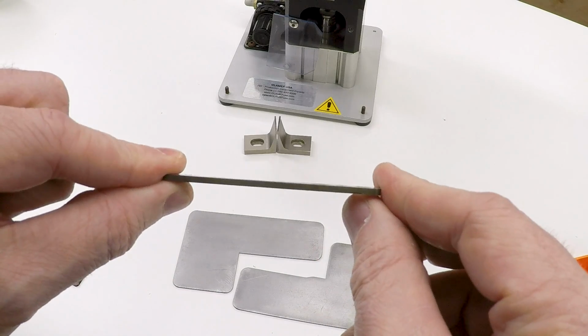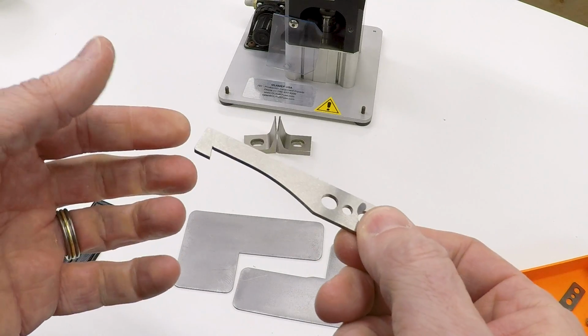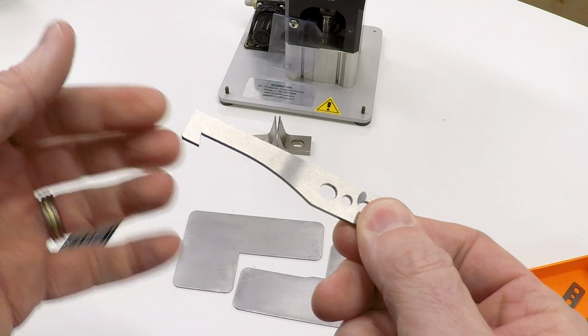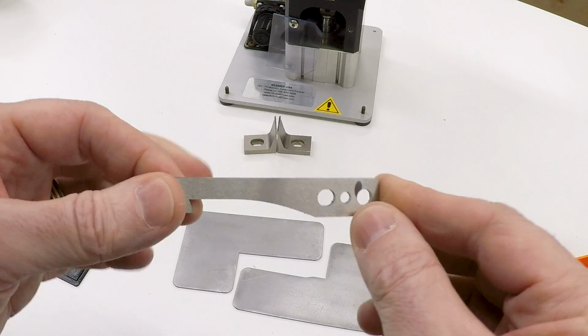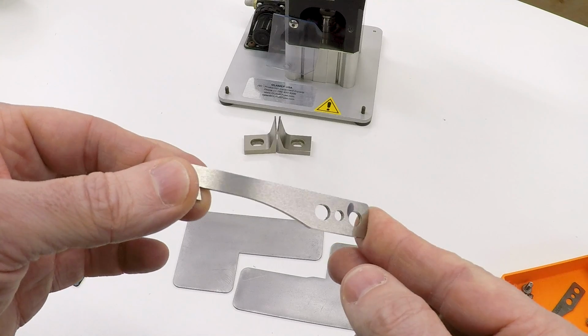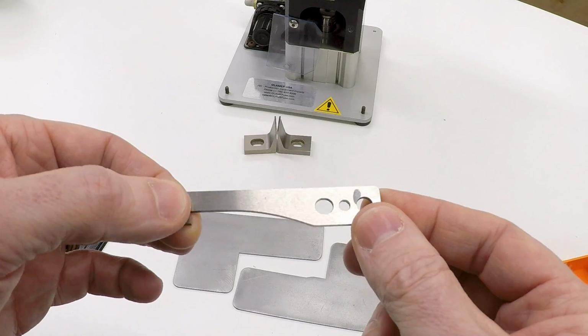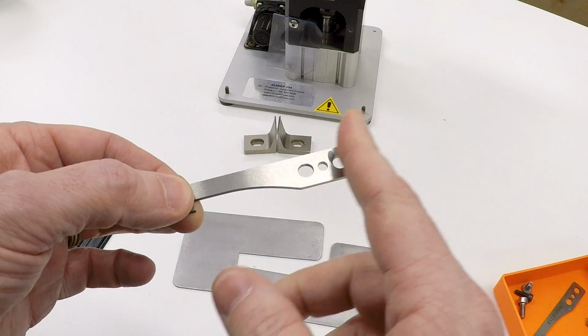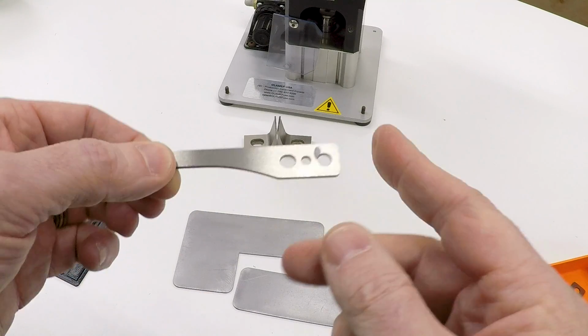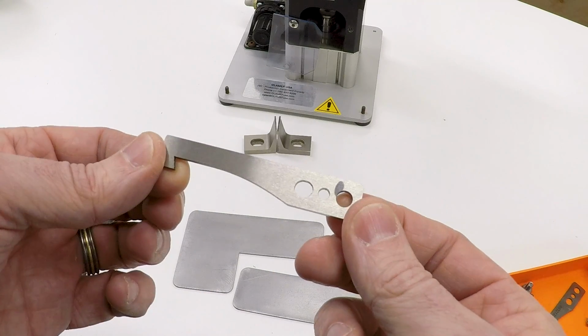The other thing that we learned is that this D2 steel, at least the way I heat treated it, had a lot of residual stress. I don't know if that's because of the plate quench, because it quenched so quickly or unevenly, as opposed to an air-cooled quench, which is what D2's usually intended for.